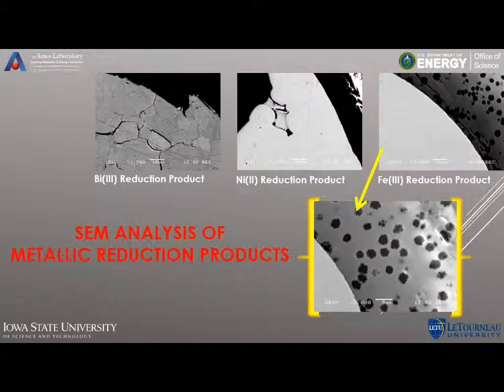Here I also brought a blown-up image of this sample on the far right, the iron-3, and I was looking at these dark areas that I saw in apparent oxide material. And those I also analyzed under SEM to check what elements were present, but I couldn't really get a good reading. I thought it might be carbon, the carbon nanotubes conglomerating together, but I didn't really get a good carbon reading. And we also earlier checked these by Raman spectroscopy, which basically looks at the covalent bonds in the material, and we couldn't get a good carbon-carbon bond read for these dark areas.